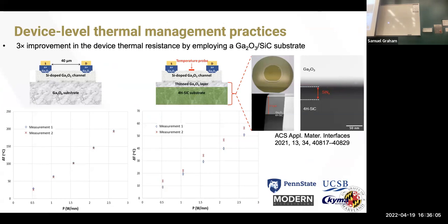And so you can see as you take the power up, this is in a term called watts per millimeter, you can see that the temperature is almost reaching 200 C. So getting very, very hot. Now, if he bonds this to 4H silicon carbide, you can see at the same powers that we're not even reaching 60 C in terms of temperature. So he shows that, yeah, this is actually going to work if you can actually do this. And so again, wafer scale, you can now take these and make these devices and show that you can really do cooling for this structure.